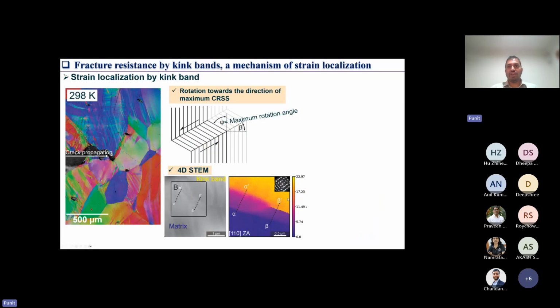And in this 4D STEM, if you look there, you can see the distribution of misorientation is different from one location to another location, which suggests that edge dislocations don't perfectly line up everywhere to give you this perfect tilt boundary. But from this diffraction pattern, we did confirm that kink band boundaries are tilt boundaries.